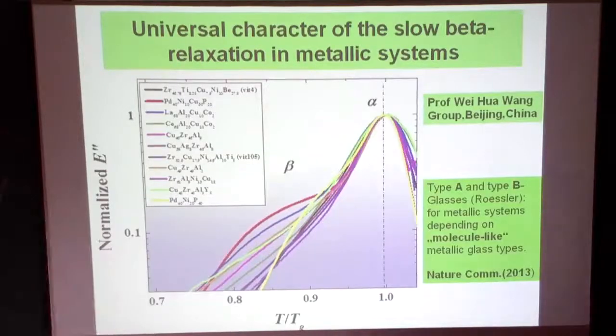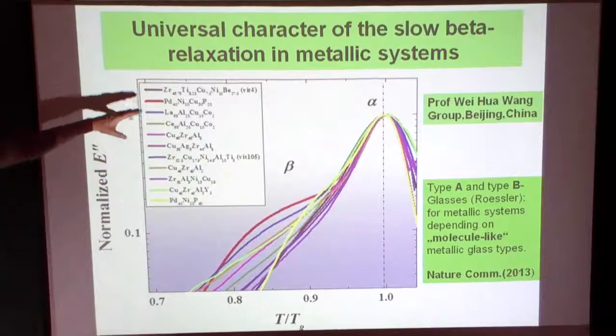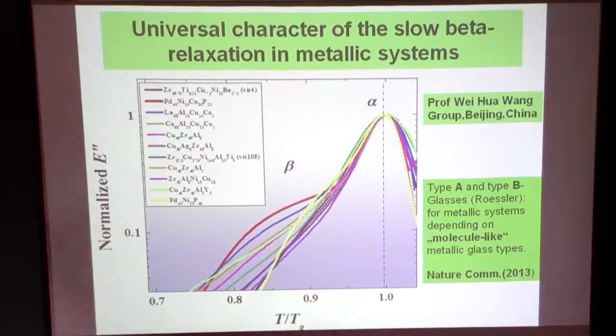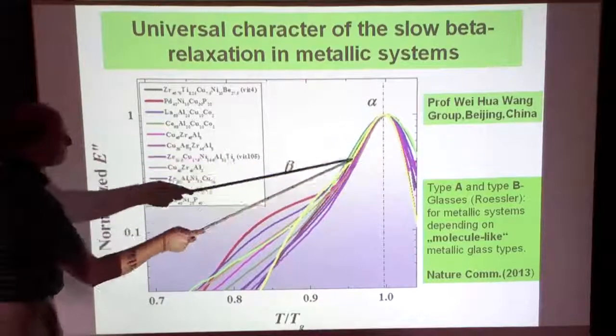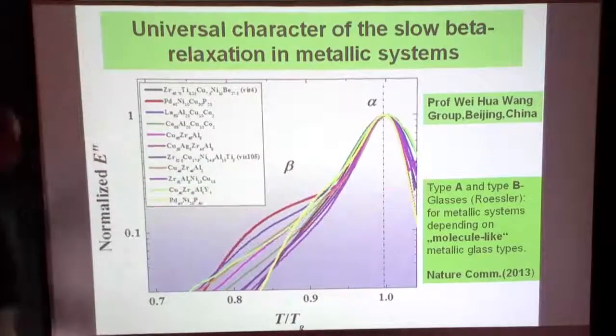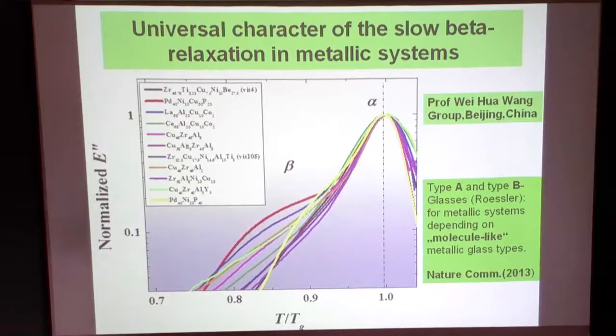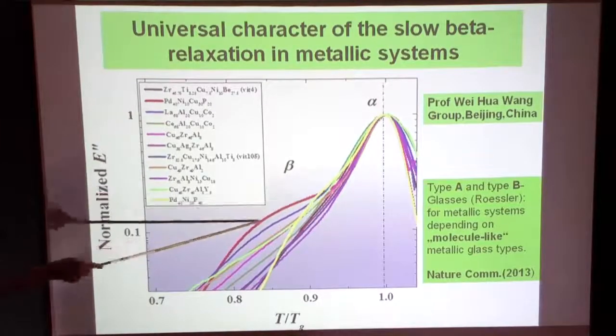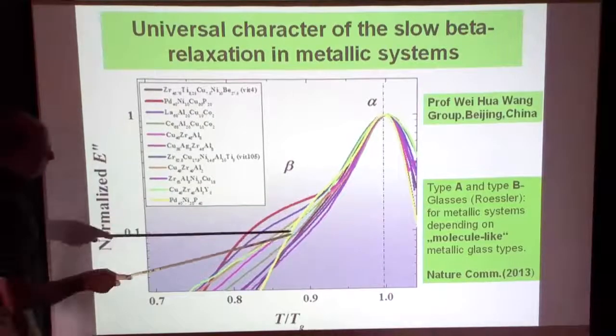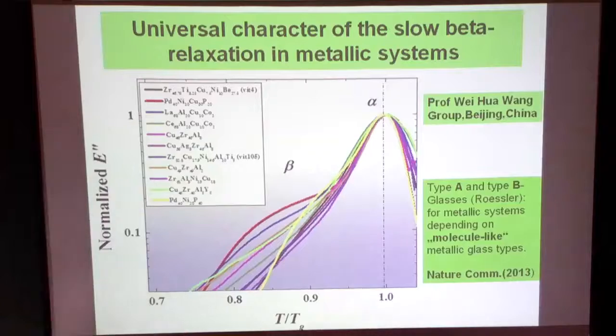Okay, here we go again to our secondary relaxations. This is work from Wei Hua Wang's group in Beijing. They analyzed a whole bunch of different systems, and what they find is that you always get this nice alpha peak. Then in the discussion of glasses and liquids, there is a group in Bayreuth in Germany, Rössler, who said we have type A and type B glasses. Type A shows a secondary peak very clearly, and type B are those which have more or less just a wing. We have an argument now that it depends very much on the alloying. Little additions of a certain type of component make a system mechanically very different.